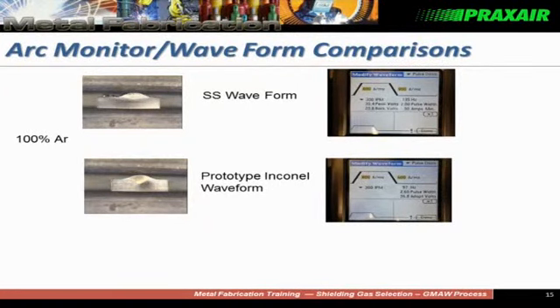Here what we're looking at is a pulse power supply with a waveform that was developed for stainless steel. We're using 100% argon, and you can see this bead on plate. The bead has a fairly high crown, not too much penetration. And this is kind of what the waveform looked like. Taking another type of waveform developed for specific types of nickel alloys, what you can't see here is a little bit of shadowing, but the bead is actually a little bit flatter but has much deeper penetration. So again, by changing this waveform using the same materials, we've affected the bead shape.